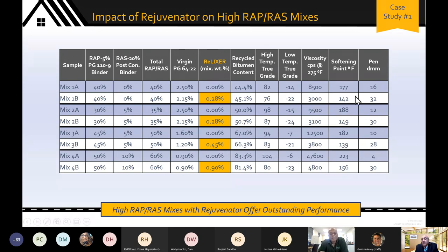Look at the penetration value. You had a stiff penetration of 16, you're able to get it to the 30 plus range. That is, again, quite familiar to folks in Europe, folks in UK, and so on. As you move down from mix 1 to 2 to 3 to 4, what's changing is what's known as ABR, or the recycled bitumen content. What that means is how much of the total liquids in your mix is coming from recycled content.